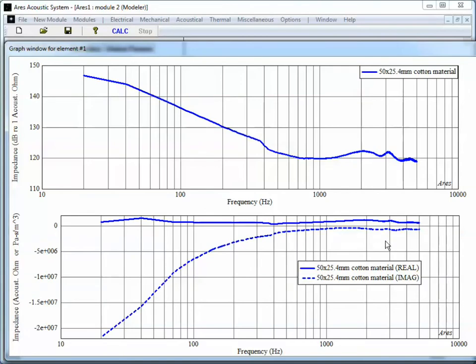So here's the cotton impedance. The magnitude in dB is in the upper graph, and the real and imaginary part of the impedance is in the lower graph. At low frequencies, the impedance is dominated by the compliance of the air volume. And at high frequencies, the imaginary part's going to 0, and the impedance is being dominated by a real part. The real part comes from the viscous losses of the air trying to force its way through the pores of the material. And that will end up dominating the impedance of this material as the frequency goes up.